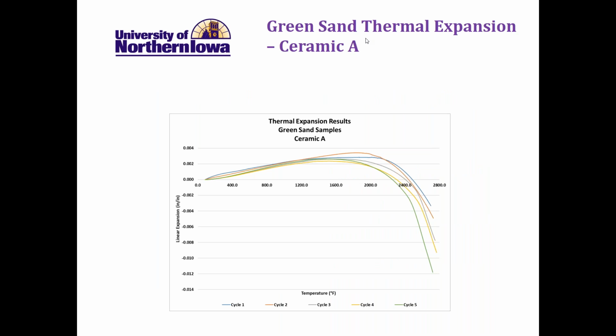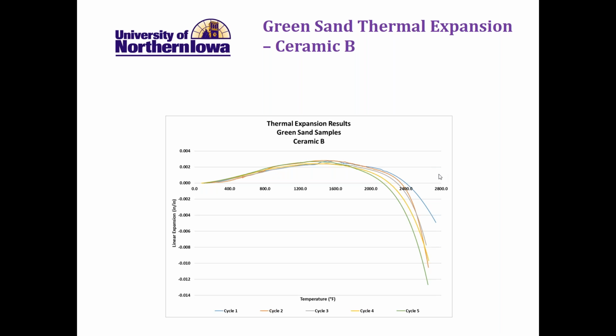Looking at the green sand thermal expansion, and these were all bentonite bonded samples, we can see the ceramic A has a minimal amount of expansion. Silica sand will have around 0.14 inches per inch. These aggregates had less than 0.004 inches per inch peak expansion. We see the ceramic material coming back to 0 or losing some dimension around 2400 degrees F. Ceramic B, slightly under 2400 degrees.